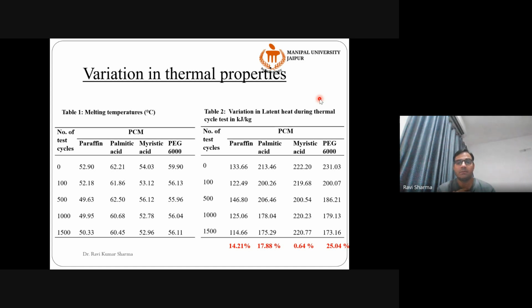That means, as a real application engineer, I can tell my customer that I guarantee polyethylene glycol will lose exactly 25% after 5 years. But I cannot guarantee on myristic acid, palmitic acid, and paraffin because their behavior is like a sine wave, increasing, decreasing, increasing, decreasing. I cannot comment on their applicability and durability. So your customer will understand that PEG has trustworthy values. I can trust PEG. Now it's up to me whether I want to use it for 1, 2, 5, or 10 years, but I know that after 5 years it will lose 25%. Still, if I can manage with 75%, I'll go with it. But I cannot trust myristic acid, palmitic acid, and paraffin. So a real application engineer has to see the pattern of these values.